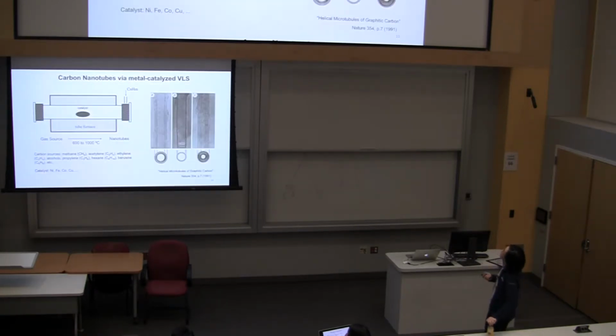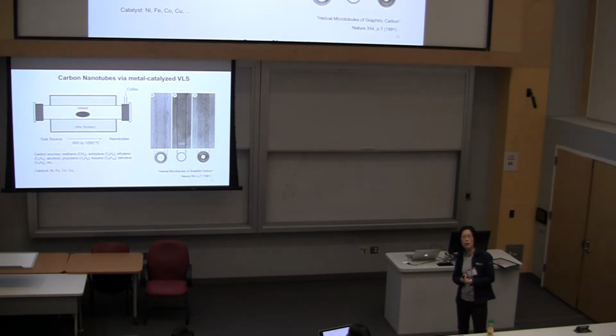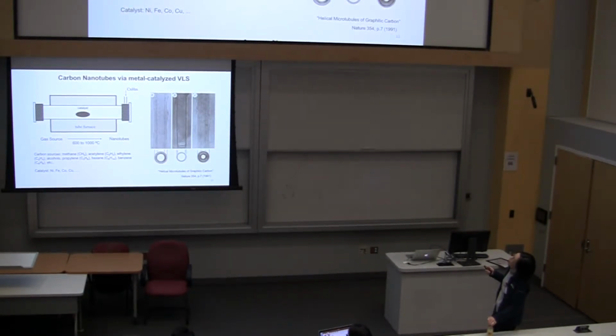Okay, so here is an SEM image of the gold particles and a long, high yield of silicon nanowires at the end. You can expand. So VLS actually, when we were growing carbon nanotubes in the late 90s, same thing. We would use, let's say, metal catalysts, iron nanoparticles. You flow carbon-containing gases at high temperature so that these gases will decompose, right? And then the carbon from these gases will be soaked into these metal catalysts. Again, supersaturation, and tubular structures can come out. And you can somewhat control the diameter of the nanowires by controlling the size of the particles. Okay?